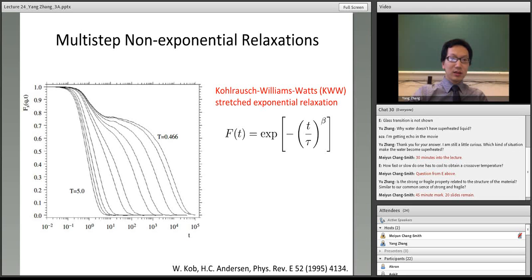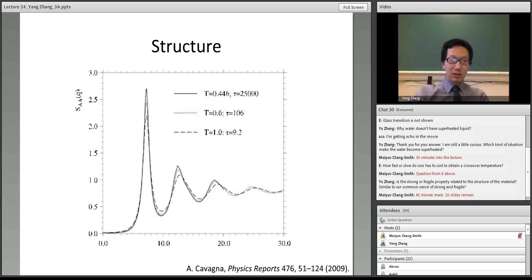All right, so go back here. In this slide, it's very significant. You can see that as the temperature changes very little, the structure doesn't change, but the relaxation time changes by several orders of magnitude. The reason I want to show you this figure is also because this is something that we can measure with a neutron scattering experiment. As you have gone through the course, you know that we can detect the structure factor with a neutron diffraction experiment. In the next few slides, I want to show you some more phenomena of glass forming liquids or glasses, and most of the properties can be directly measured by neutron scattering.